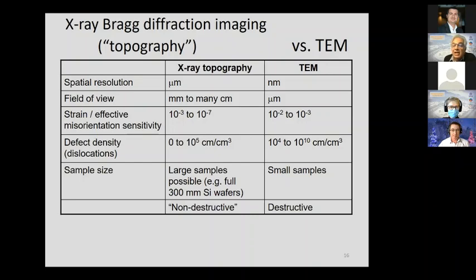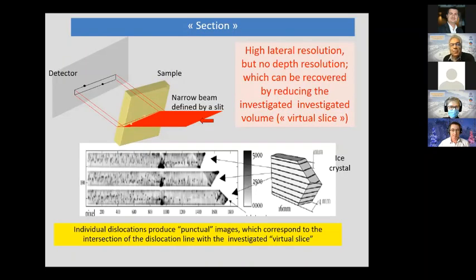The sample size: you can look at large samples with X-ray topography, for instance 300 millimeter silicon wafers, and you have small samples in transmission electron microscopy. X-ray topography is non-destructive. Of course, transmission electron microscopy is destructive.